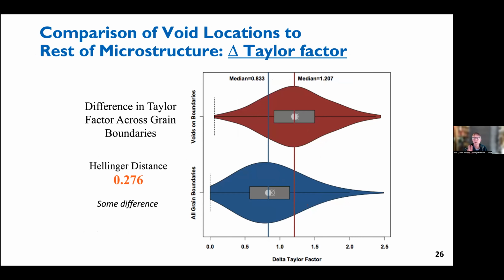And so there were only two things very closely related to each other that seemed to show any separation in these two distributions. One was to look at a quantity that is called the Taylor factor. So the Taylor factor is something very specific to what we call crystal plasticity. In other words, the study of how you relate dislocation slip to external stress strain behavior. And Taylor factor is a scalar number that more or less tells you the ratio between the slip system strength and the macroscopic strength that you can observe. And so in this case, we did find some separation in terms of the difference in Taylor factor across grain boundaries. We measured it with Hellinger distance. It's a bit equivalent to a correlation coefficient.